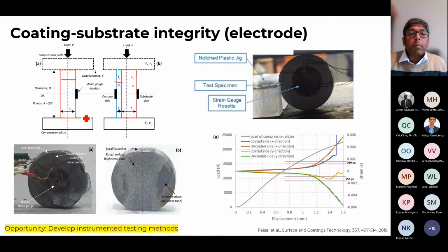Normally, you use diametral compression on rock samples, on a quartz sample, to find out the geomechanical behavior of those core samples. However, in this case, we took a small slice, like a disc shape. On one side, we did the coating using plasma spray and put strain gauges on either side. You compress it on a huge machine, and then try to see the strain as you compress.